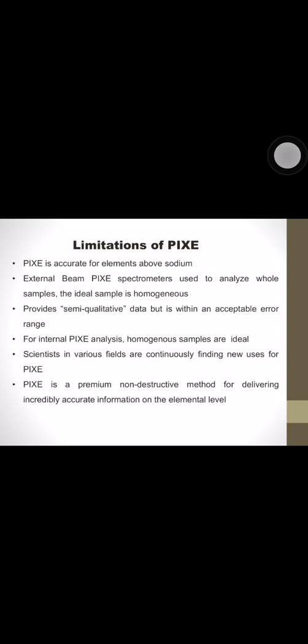Limitations of PIXE: The limitations of PIXE are primarily in regard to what elements it can identify. PIXE is accurate for elements above sodium. Anything below sodium will not show up as the element's rays will absorb the barrier to reaching the detector. While external beam PIXE spectrometer can be used to analyze whole samples, the ideal sample is homogeneous.